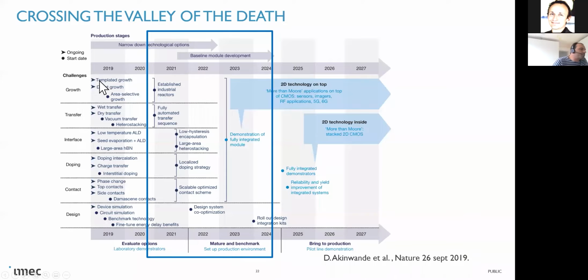So, for example, for growth, we have different options. You can grow epitaxially eventually on a dedicated template, so van der Waals epitaxy, or you can try for a direct growth on an amorphous dielectric, for example. But the quality of the material will be maybe very different, and this will define where you can use that material or not. Or you can try to do area selective growth, so you have a controlled seed deposition, and then you grow a single crystal around that seed. This is not very mature, even in the lab. Not a lot of people have demonstrated that. It is demonstrated for graphene, but for TMDCs, it's still very immature.